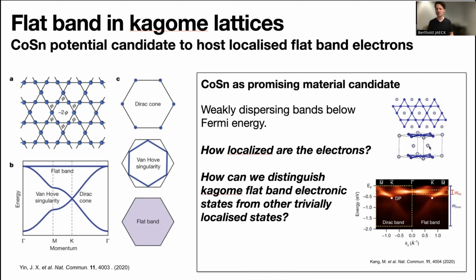Moreover, cobalt tin turns out to be a paramagnet, and it doesn't have any long-range magnetic order. Of course, this can be challenging to analyze theoretically, but the clear benefit is that the flatband is not subjected to any sort of magnetic exchange terms that are known to destroy, for example, the flatband of iron tin or even Fe3Sn2. Now, it didn't take long until people could detect this flatband using ARPES measurements, where it appears as a rather narrow band, a little bit below the Fermi energy.